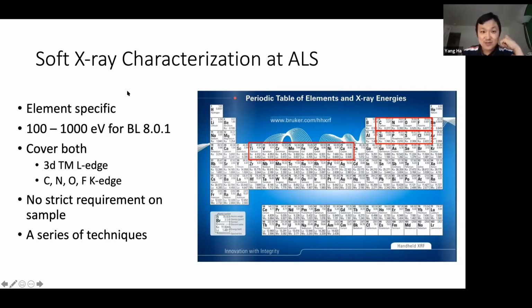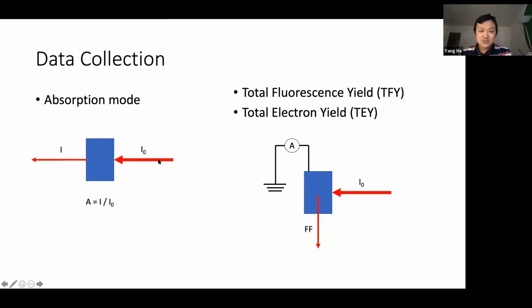And notice when I say X-ray spectroscopy, I really mean a series of techniques. So a standard X-ray absorption is you're measuring the outcoming photon versus the incoming photon at a given energy. But this is not realistic for soft X-rays because your samples will not be transparent to soft X-ray. So instead, we can measure the total fluorescence yield. We can put our detector at 90 degrees to collect the coming out fluorescence photons, assuming the amount of fluorescence is proportional to the amount of absorption. And we can also measure the total electron yield. We can measure the compensation current.